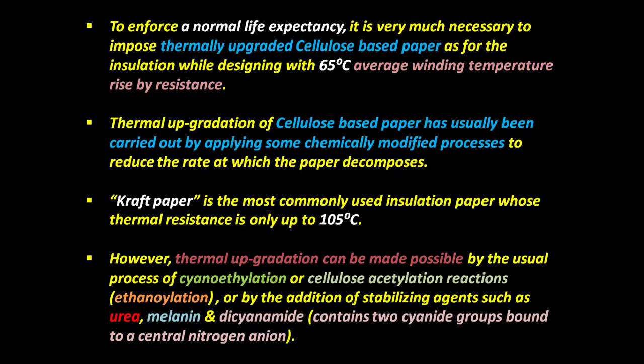Thermal upgradation of cellulose-based paper is usually carried out by applying chemically modified processes to reduce the rate at which the paper decomposes. Kraft paper is the most commonly used insulation paper whose thermal resistance is only up to 105 degrees centigrade. However, thermal upgradation can be made possible by the usual process of cyanoethylation or cellulose acetylation reactions, or by the addition of stabilizing agents such as urea, melamine, and dicyandiamide, which contains two cyanide groups bound to a central nitrogen anion.